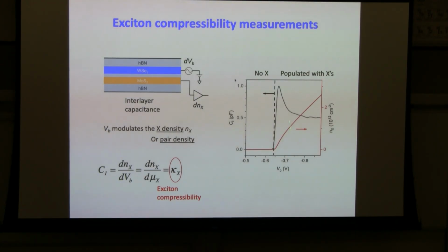Yeah, unfortunately, this exciton compressibility measurement is not sensitive to superfluidity in excitons. You can see that the interlayer capacitance is very large at the beginning when you inject excitons into the system. It's just telling you that it's way easier to inject a dipole compared to injecting independent charge. Oh, I see. Actually, it's a measurement of the exciton-exciton interaction. It's not sensitive to the superfluid phase, not sensitive to phase coherence. Yeah.